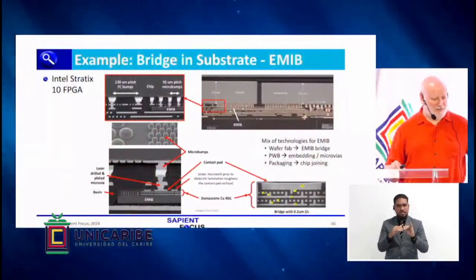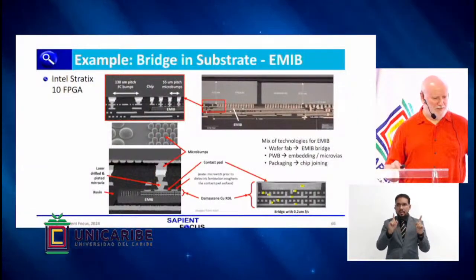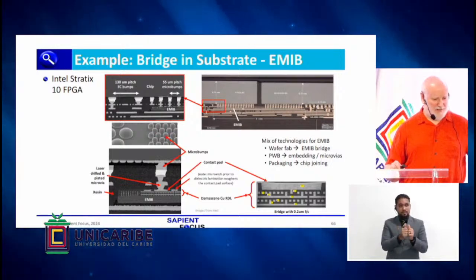So this is an example. This is an Intel part, an FPGA, field programmable gate array, where they're using bridge chips. You can see there between the FPGA itself and some transceivers that are on the package substrate, and embedded in the substrate is the bridge chip. And this is the same part, and you're looking at that left middle picture. You're looking at the density difference between the micro bumps that attach to the silicon bridge versus the bumps that attach to the substrate. So you can see the density and pitch difference there.